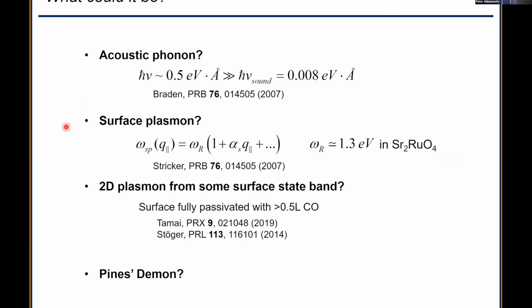Another thing one might guess is that it's a surface plasmon. Surface plasmons are gapless. If you open Ashcroft and Mermin, they show you that surface plasmons always go to 0 frequency at 0 momentum. In this case, the velocity is far too low. The reason surface plasmons are gapless is that at small momentum, they become polariton-like and they mix with a photon. And actually the gaplessness is because a photon is gapless. It turns out that regime happens at such low momentum, it can't be measured with massive particles.